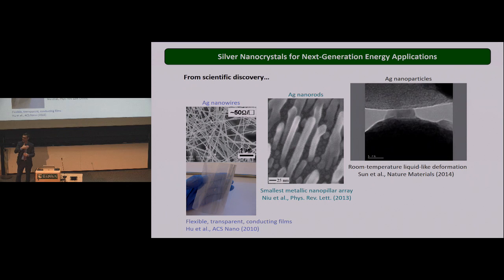So that's what the atomistic simulation showed: yes, it's an interplay between the roughness, the crystal slip, and the surface diffusion. You need to have plasticity and diffusion. And what we show is it is the plasticity that initiates that diffusion on the surface. If you have a nanowire that's perfectly smooth, perfectly straight, you will not see any surface diffusion, and this effect will not happen. You have to have some defect on the surface. The steps need to be present. Okay. I hope I addressed your question.